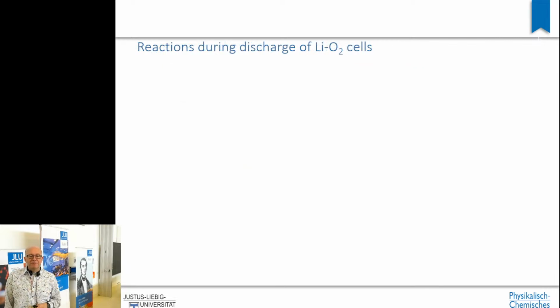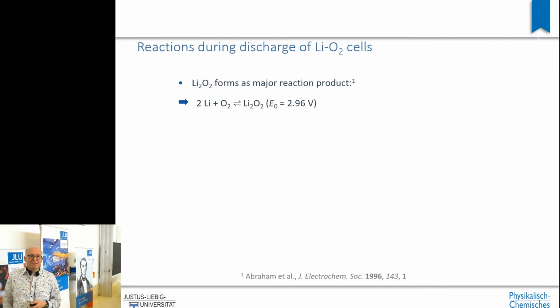And we will see what is very important, that in fact species are formed that still have at least a single bond. So the molecule should still be kept, because if the oxygen molecule is broken up completely, then it is very difficult to recharge this cell, because reforming the molecule takes too much energy, too much overvoltage, heat, as we express that in electrochemistry.